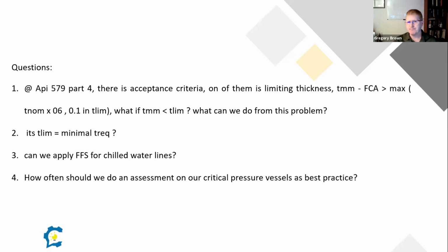Now, part of the question that comes up is, what situation are you in? A good example, I was just recently looking at equipment that was chilled water, but the chilled water was actually used to cycle a piece of equipment where they had to bring it down from elevated temperature as part of their chemical processing. It was actually a pharmaceutical industry. They had to use chilled water to cool the vessel down so they could reload it. Anytime you take hot equipment and impact it with cold liquid, what happens? You get significant thermal stress. This was causing fatigue cracking, which then propagated and was causing failure of those lines.